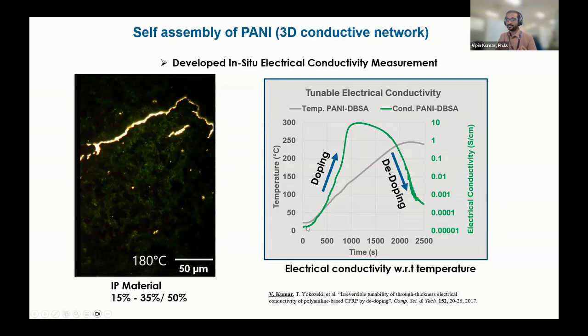So doping is adding the proton to the chain of polyaniline, and de-doping is taking it out. And you can see with the temperature, the electrical conductivity can go up to 6 orders of magnitude different within 1 or 2 minutes, depending on your heating rate. So this is how we made this electrically conductive resin system.